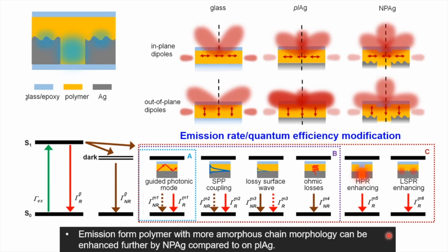Overall, we found that the emission from the polymers with more amorphous chain morphology is enhanced the most by the nanoporous silver metasurfaces compared to the planar silver surfaces. This is attributed to larger excitation enhancement associated with the out-of-plane polarized electric fields in the pores, and also the out-of-plane chain morphology of the amorphous polymers, as well as a larger quantum efficiency enhancement associated with outcoupled surface plasmon polaritons that are coupled better by the out-of-plane dipoles.